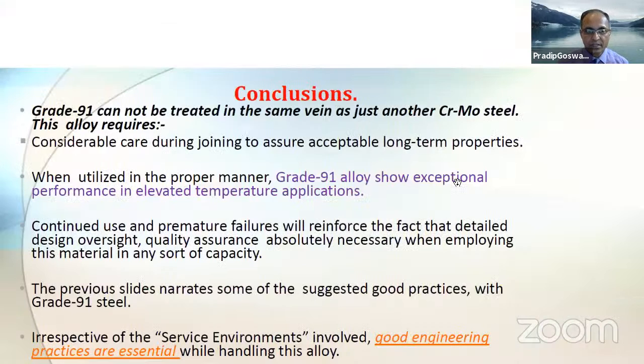To summarize, these are some of my conclusions. Grade 91 cannot be treated in the same vein as just another chrome moly steel. This alloy requires considerable care during joining to assure acceptable long-term properties. When utilized in the proper manner, grade 91 alloy shows exceptional performance at elevated temperature applications. Continued use and premature failures will reinforce the fact that detailed design oversight, quality assurance, as well as the welding practices are absolutely necessary when employing this material in any sort of capacity.